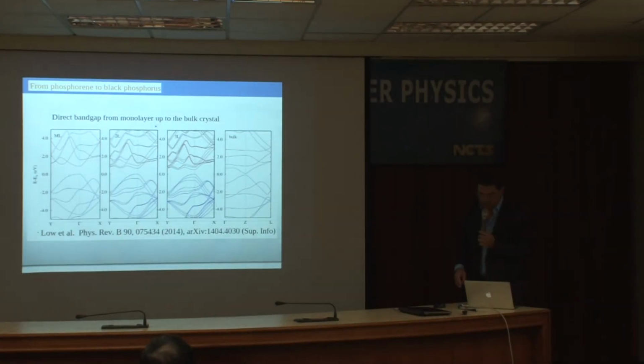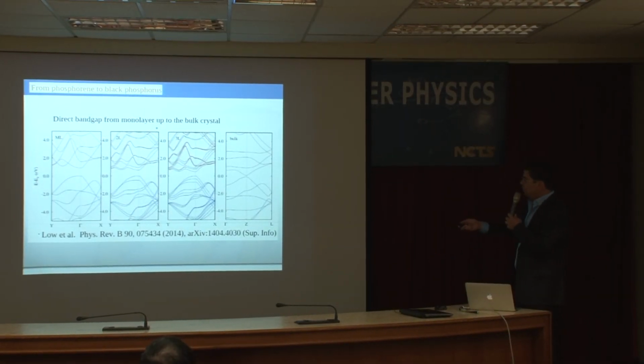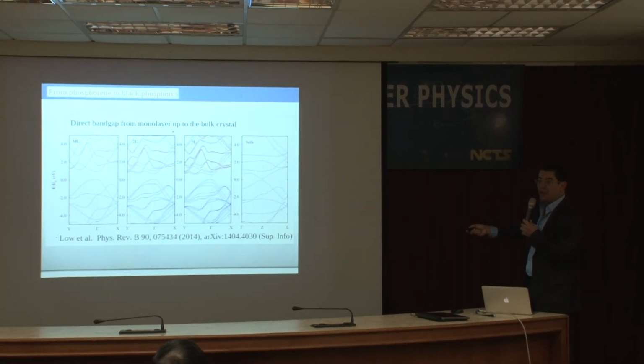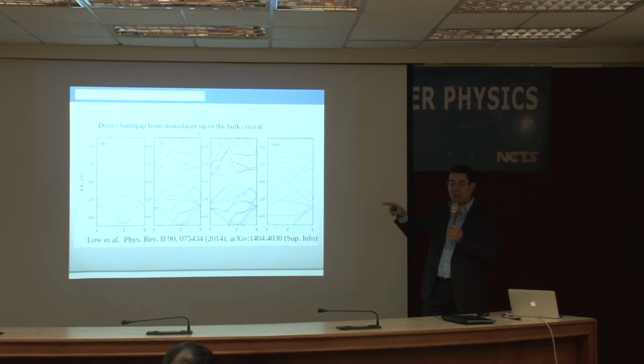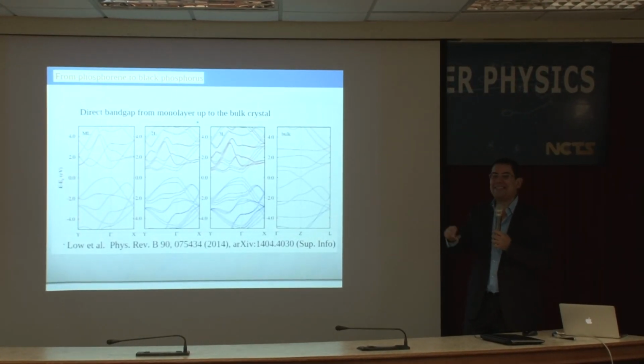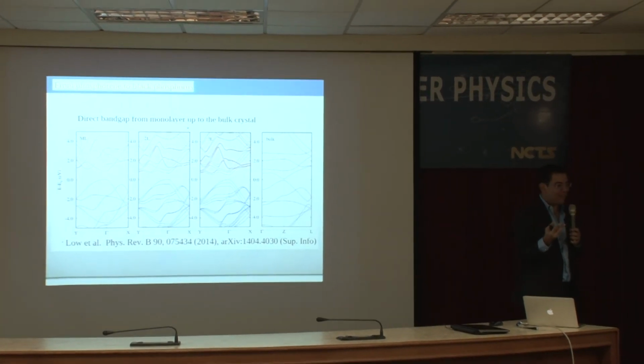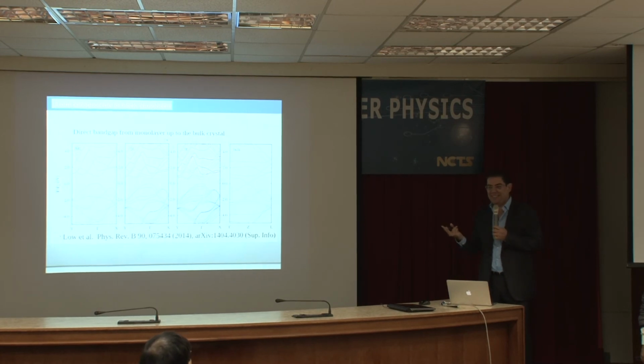So you probably cannot see very well on this slide, but you see here in the valence band, it's actually very flat. There are two valleys. Okay, so all these materials have two valleys in the conduction and valence band. So now there is an interesting thing. You have what people call valleytronics, because using polarization of light, you can choose what valley you excite. And if you have spin orbit coupling, you have spintronics together with valleytronics. So the number of combinations essentially increases a lot. More quantum numbers, more interesting physics. Thank you.